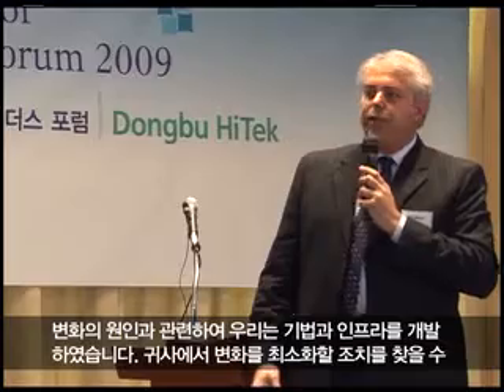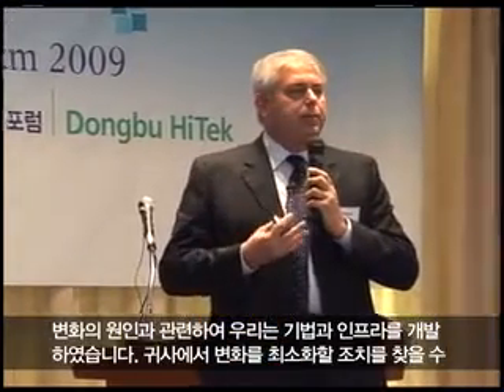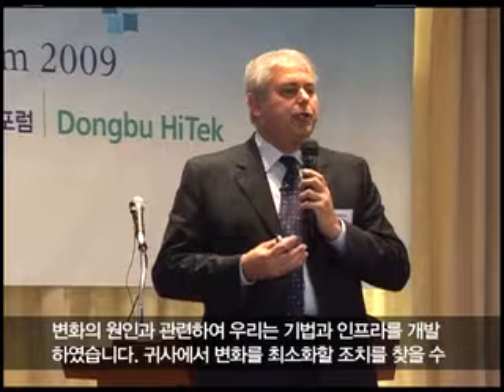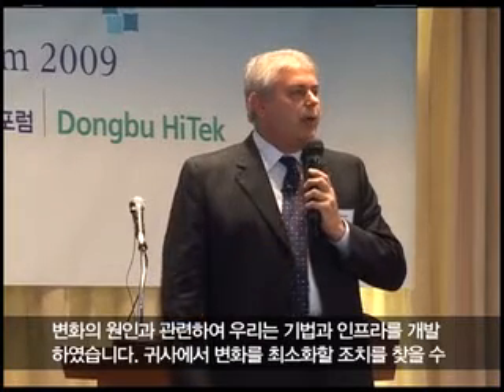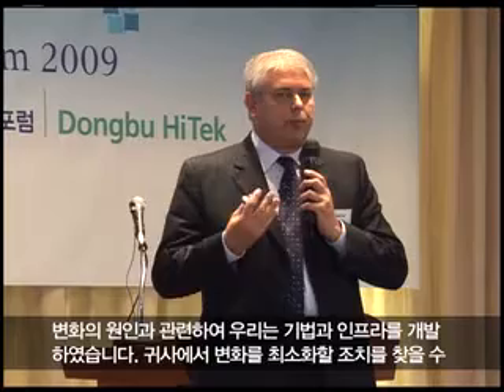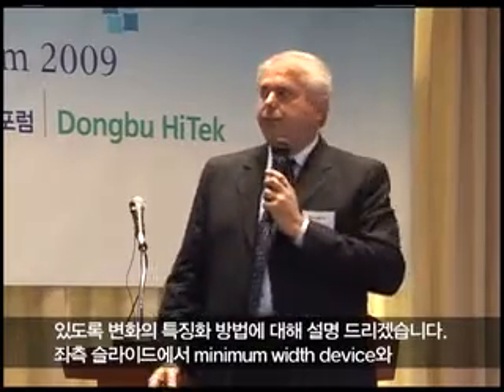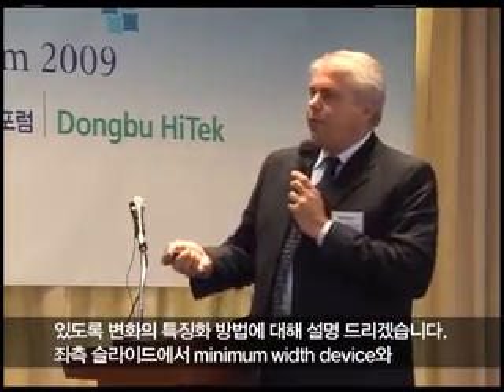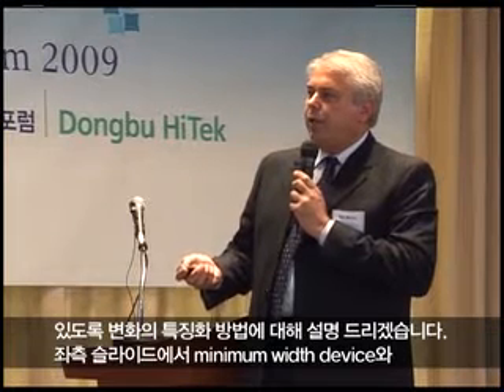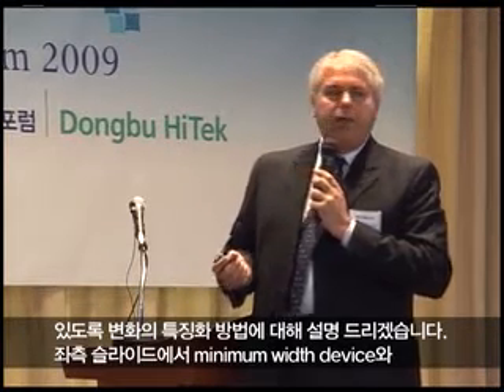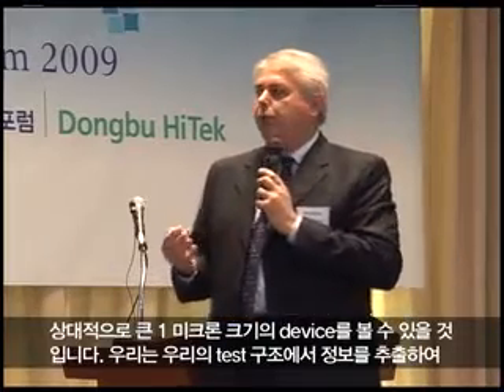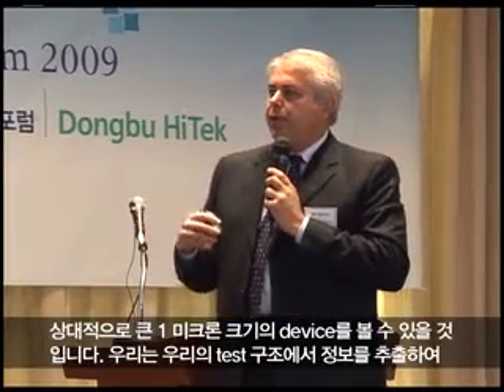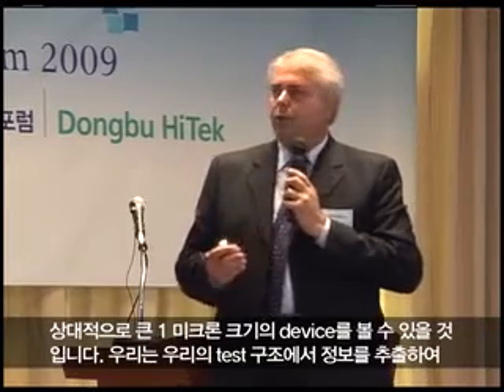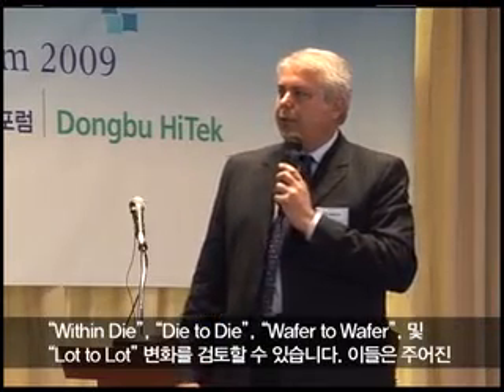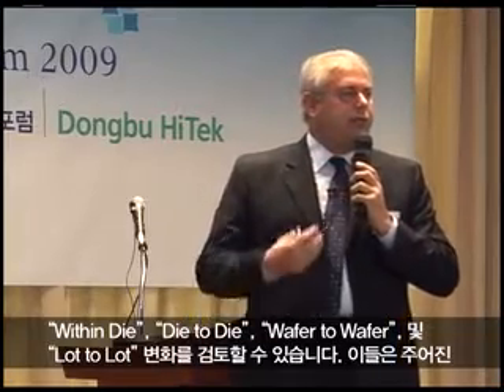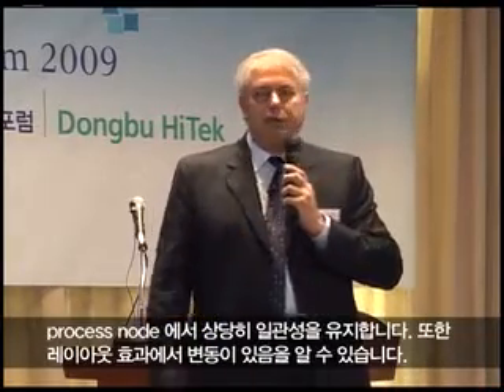So on the sources of variation, we have developed techniques and infrastructure that I'd like to explain to you, of how to characterize this variation so that you can properly define your actions to minimize it. You can see here on the left side that we have minimum device width and 1 micron device width, relatively large. And we can extract information from our test structures to look at the within die, die to die, wafer to wafer, and lot to lot variations. And we find these things to be very consistent on a given process node.